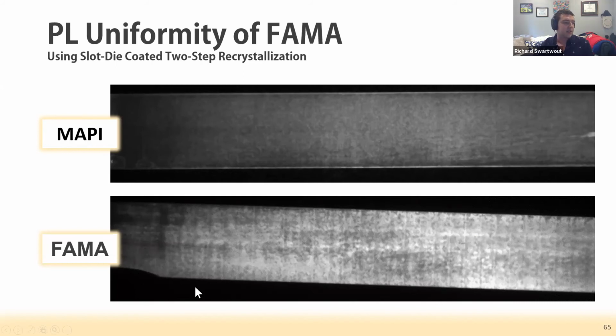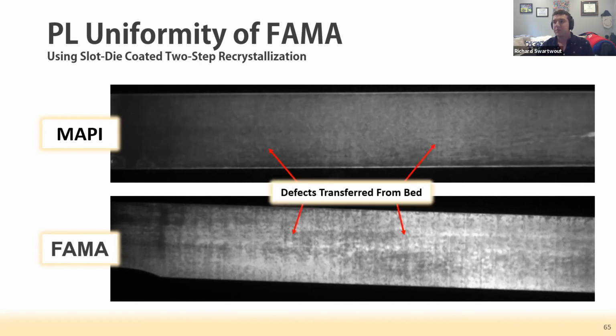This lead-in defect here is common on small-scale sheet-to-sheet coaters. But I want to point out that the speckling and line-based distribution are actually defects transferred from our vacuum bed—the vertical lines are rough machining marks, and the speckling is due to the hole patterns in the porous aluminum chuck. So none of these defects are fundamental to the ink system or the method; they're actually hitting the limitations of our proofer.